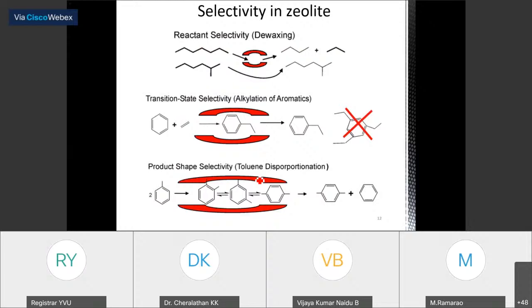Then I told you that zeolites exhibit selectivity. So they can exhibit reactant selectivity as well as product selectivity. These are the three types of selectivities which are exhibited by different zeolites based on the shape and size of the pores which they have. For example, in this case, I have a linear alkane and a branched alkane. The linear alkane easily passes through the pores because the size and shape of the pores allow this molecule to pass through. But the branched chain alkane is not able to pass through. In this way, this zeolite is imposing reactant selectivity.